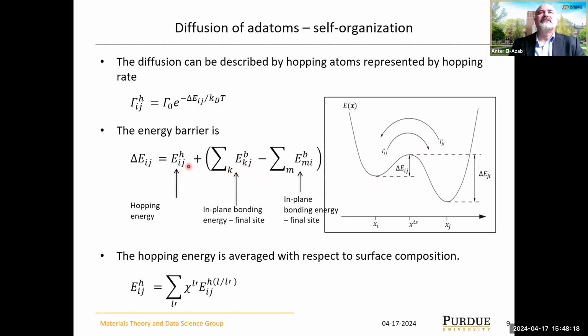Those two energies are the energies of hopping, assuming that the hopping species is not constrained by any neighboring atoms, with a correction coming from the bonding at the initial site and the final site here. You can call this the thermodynamic effect, because it's just a term that depends on the difference in bonding between places. If this leads to phase separation, these will be the energy quantities that give rise to a difference in bonding energy or free energy between a mixed state and a phase-separated state.